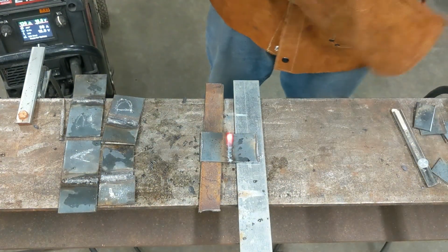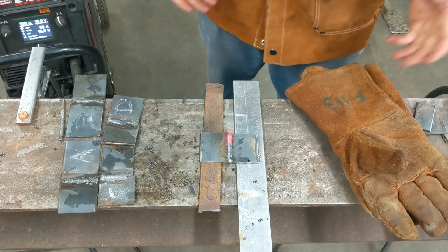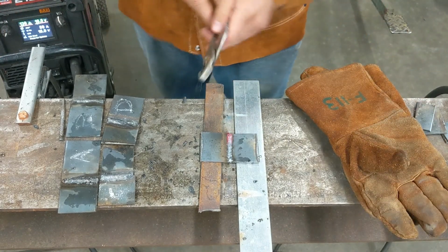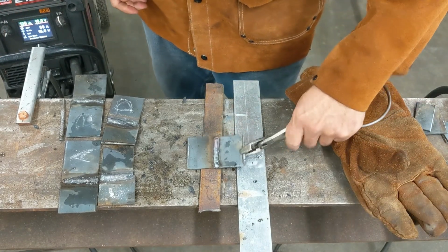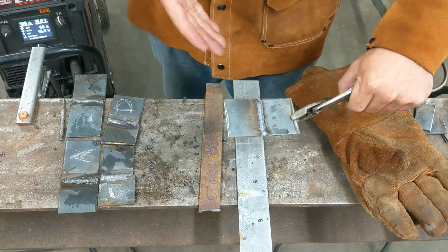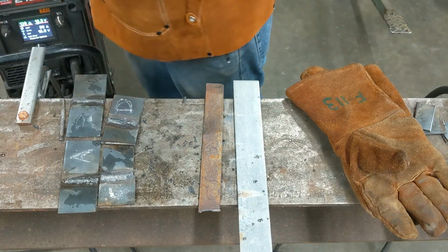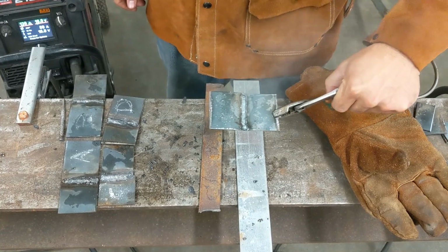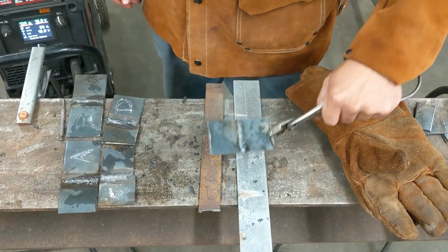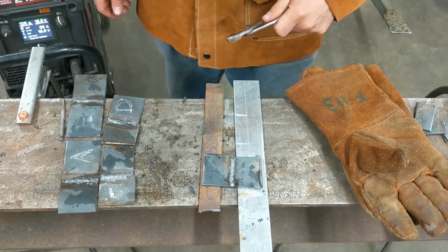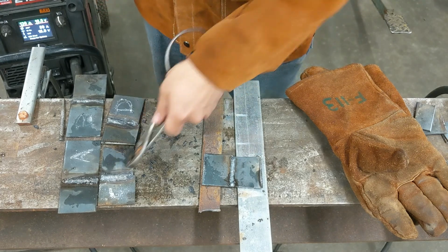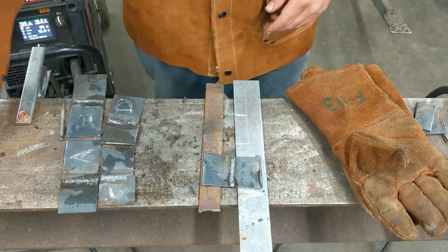So definitely a distinctly different sound, as well as a distinctly different appearance of the weld itself. That's a very clean weld. There's no flux to hammer off. Very good weld penetration. This can go on to paint without having to be cleaned the way the shielded metal welds do.